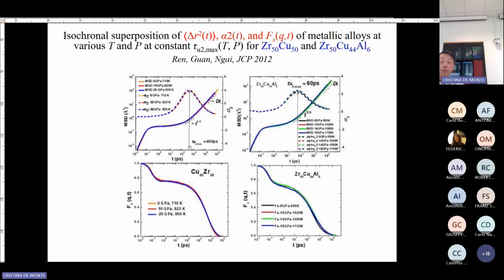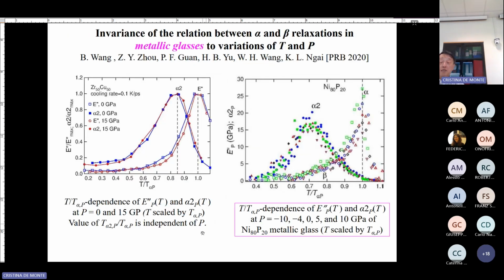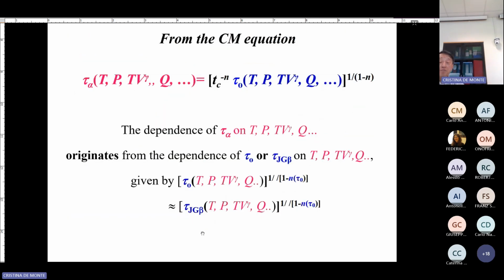I collaborate with a Chinese group that do very good simulation in metallic glasses, and then we found the same thing. I won't bore you with that detail, but it's there. So it's again different combination of pressure, temperature, and in this case the mean square displacement. But it's another way of showing alpha, beta in a way, and it's the same thing. Okay, so let me skip a little bit.